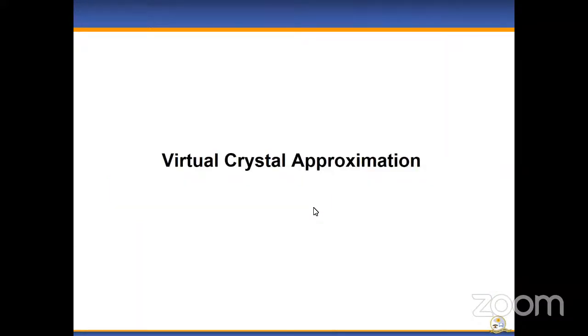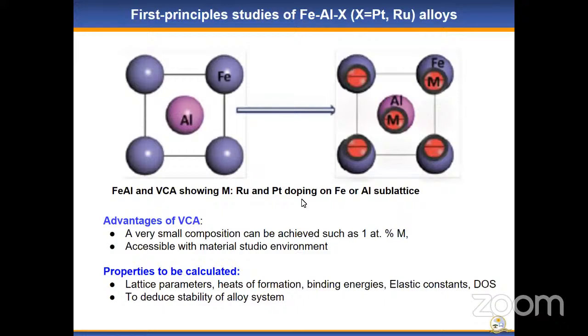And then the next one that I want to show is that one can also use the virtual crystal approximation to design or predict new materials. What the VCA does here is that you work only on a very small, one unit cell, which can then be used to create a number of alloy compositions from 0 to 100%. How we create that is by choosing which substitution you want to make. In this case, we were doping with some elements on both the iron sublattice and the aluminum sublattice. So you can choose to dope in one, depending on which composition you want to reduce and which one you want to increase. And that also is guided by the application that you are actually targeting.